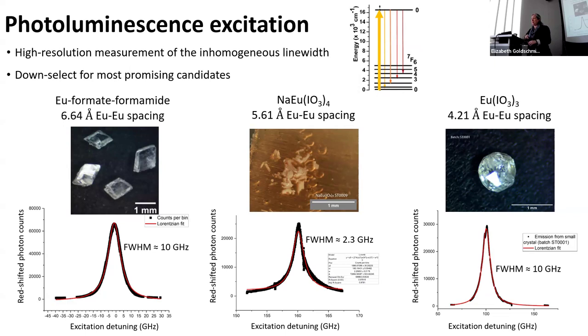So the main reason we look at different materials is to realize very low inhomogeneous linewidth, in this case, to get low inhomogeneous linewidth with high spectral density. You need to reduce the local strain, right? That's the main thing, the local strain inhomogeneity. You actually need local strain that allows the transition effectively. You need an electric field to make the transition allowed, but you want this same electric field at every.